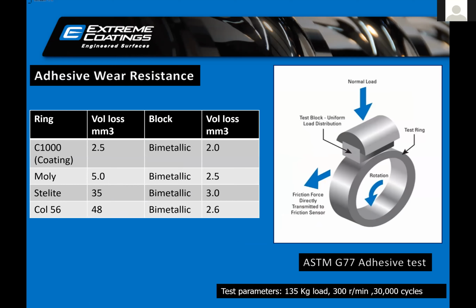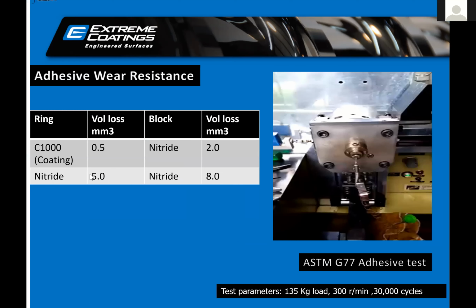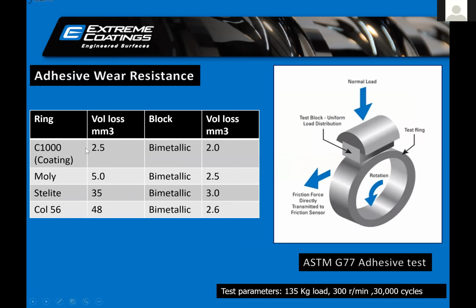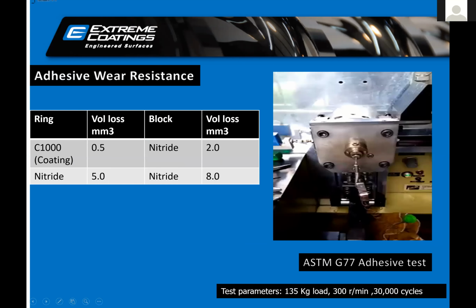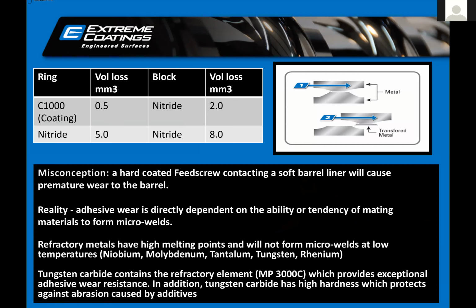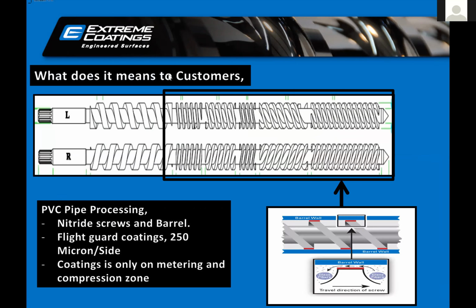And this is another test to check metal to metal wear and how it's performed. Again, compared to any other solutions available, the volume loss in the coating is minimal. So what it means to customers: if you are a pipe processor, you can take our OD coatings on the flight top, and if you are getting 8,000 hours of life, this may definitely give you 3 times the life of whatever you are getting from nitrided screws and barrels.